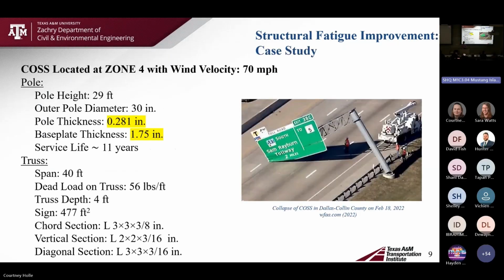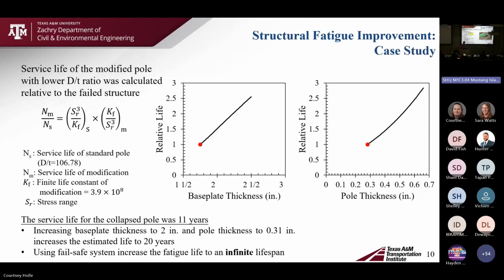And so on the left, we have a bunch of different parameters of this pole. We really want to highlight the pole thickness and the base plate thickness. In the design tables, the thinnest pole you can have is 1/4 of an inch. So you can see this pole was just slightly thicker than that, a very thin pole. There was also a relatively thin base plate, with, I believe, the thinnest base plate in current standards being 1.5 inches. So we wanted to look at what would happen if you were to shift these numbers a little bit.